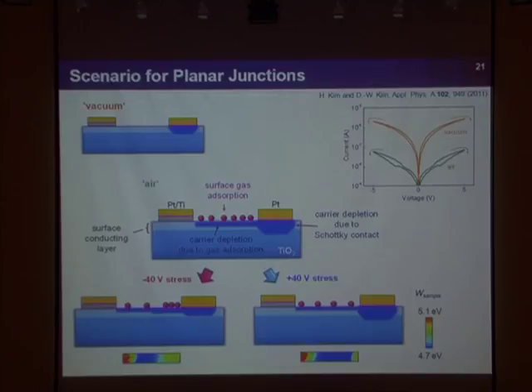The important thing is that in all these experiments, even in the previous cases, the gas environment is really important—it can affect the actual carrier concentration at the surface region. This is a very important message from both of these results. And it's quite clear that if you put the sample in vacuum, the current level increases quite a lot. That's pretty obvious.